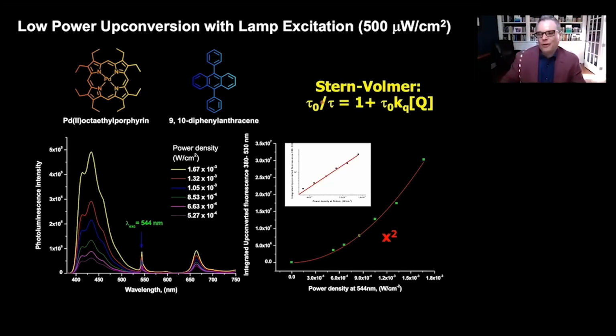Now, what does that do for you? Well, tau zero now in the Stern-Volmer expression becomes such a long lifetime that you can get away with much lower quencher concentrations. And you can do this upconversion much better because you're not going to have as many inner filtering effects from the sensitizer. So you can use lower concentrations of sensitizer and lower concentrations of acceptor. That was really critical because now this is what was amazing to me. Our first experiment with palladium octaethylporphyrin and diphenylanthracene, this is done in our fluorimeter with non-coherent light exciting right here.